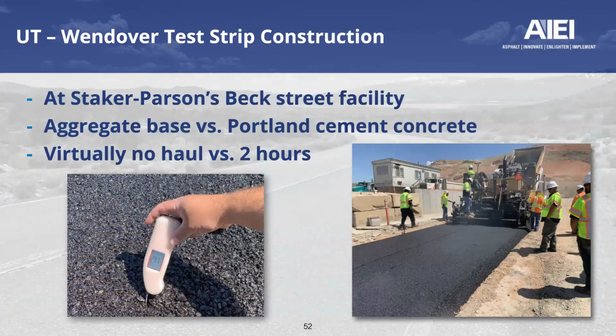Staker Parsons was very concerned and questioning their ability to get good density, full depth on a 6-inch lift. I would point you to a Mixbusters article that Dr. Buzz Powell and I did that talks about thick lift paving and the ability to get density. But Staker, wanting to prove to themselves that they could get density and also wanting to determine what might be the best procedure to achieve that density, mixed about 100 tons of material at their Beck Street facility.